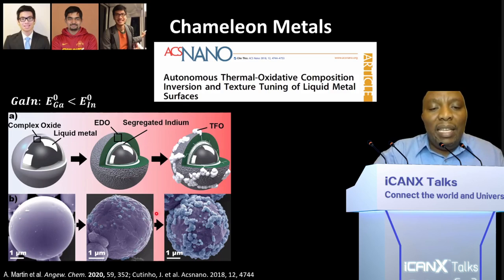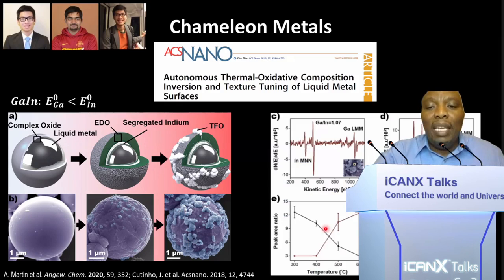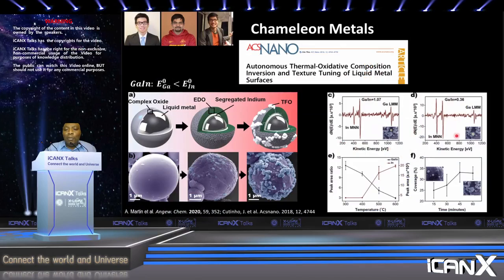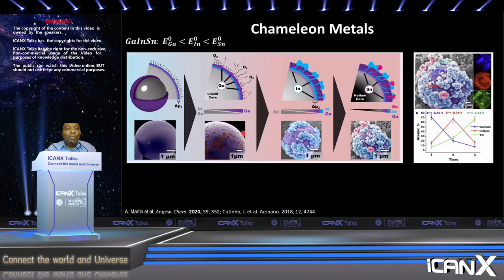And we see here, this is an example of a particle of gallium and indium that has been heated up to about 600 degrees centigrade. And you can see now the component that is on top here is very rich in indium. And we confirm the composition of the two tiers of texture by using Auger spectroscopy. And you can see the first layer is very rich in gallium, but the second layer is getting richer and richer in indium as you continue heating this. But then this is a binary alloy. The question is, what would happen when we go even further?